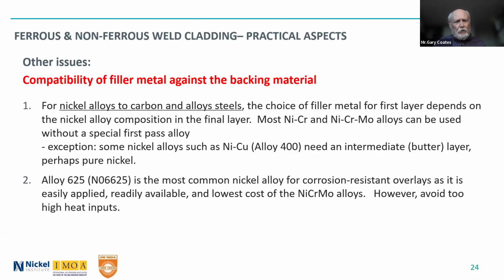Now, alloy 625, or ERNiCrMo-3, is really the most common nickel alloy used for corrosion resistant overlays. It's relatively easily applied, readily available, and of the nickel chrome moly alloys, it is really the lowest cost. So it is used extensively for weld overlays. But you have to be very careful about too high heat inputs.